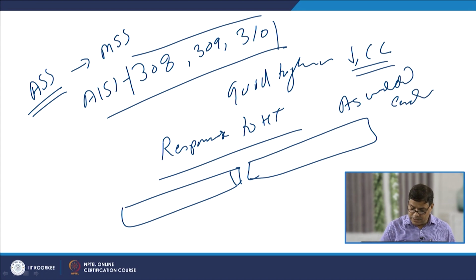In that case, the use of the austenitic stainless steel filler will help in developing a weld joint with the minimum possible residual stresses and minimum possible tendency for cracking, due to the reduced residual stresses and the reduced cold cracking tendency. So, ASS fillers are used when the weld joint is to be used in as welded condition.